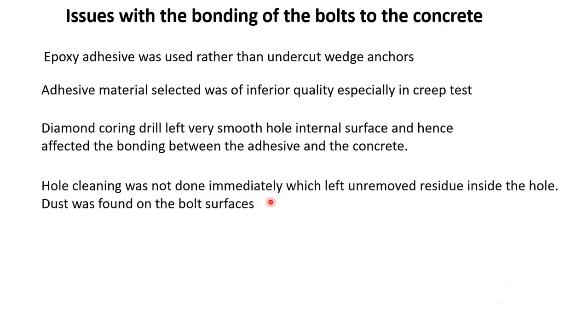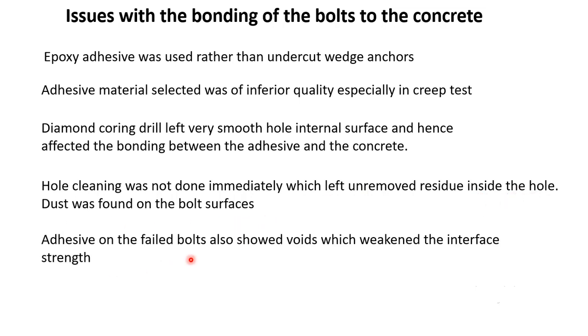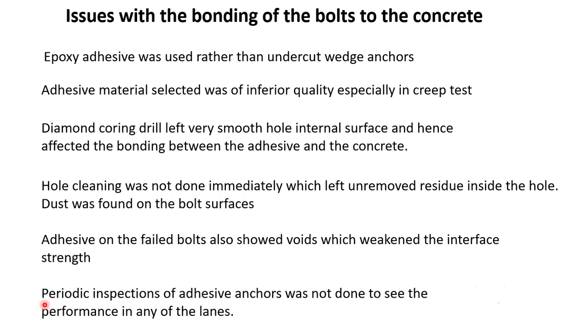Hole cleaning was not done immediately, which left unremoved residue inside the hole. Dust was found on the bolt surfaces. Adhesive on the failed bolts also showed voids which weakened the interface strength. Periodic inspections of adhesive anchors was not done to see the performance in any of the lanes. So here we can see that these were the technical issues with the bonding of the bolts to the concrete, which led to the failure.